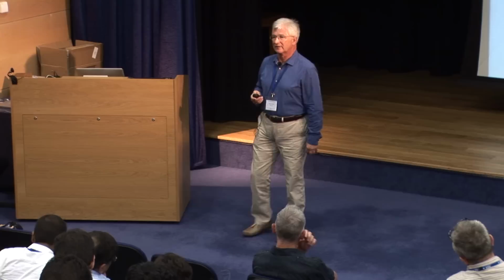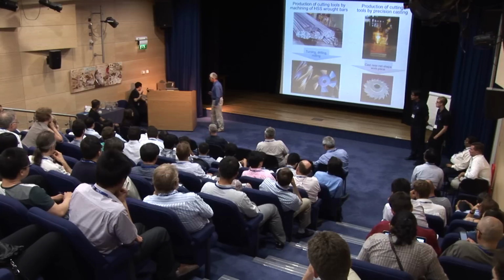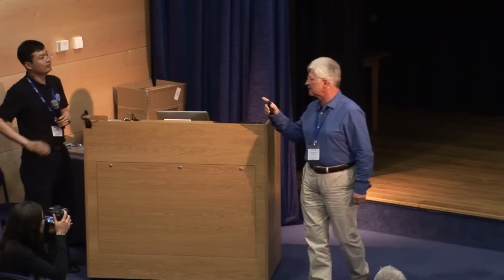Okay, there's a question online, from AK Steel Research: ferrite grain inoculate or carbide inoculate? Yes, of course, first of all for inoculating ferrite. As I said in my presentation, it's very important to have these nucleation sites for ferrite, because ferrite in the case of high-speed steels is the primary solid solution which precipitates from the melt.